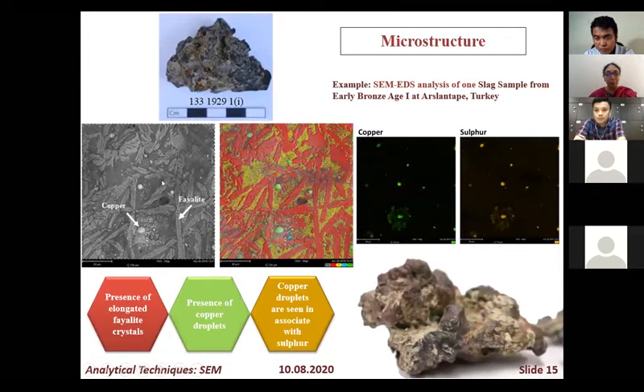Here we can see the SEM EDS analysis result. This is a backscatter image of a slag sample from Arslantepe, Turkey. You see the elongated lighter gray phase is fayalite. This is fayalite, which was also detected by XRD. And we can also see a lighter white droplet. This is copper. So now we know our copper droplet is distributed in between the elongated fayalite crystals. It is very important to know this droplet, because this copper droplet is only produced during smelting activities.